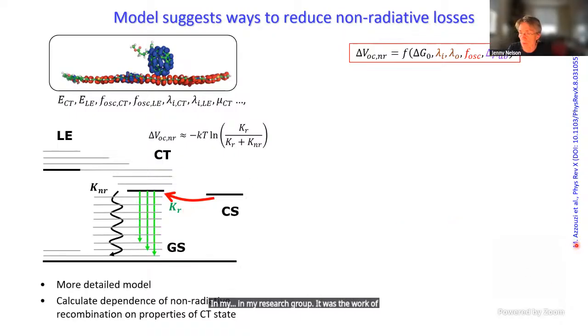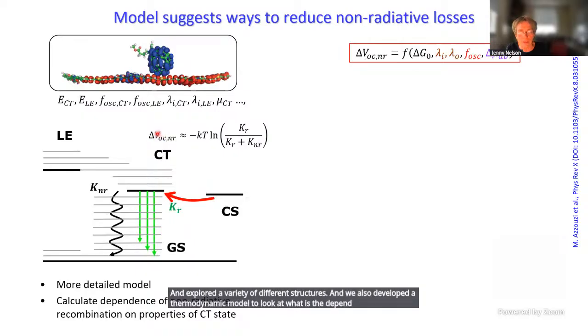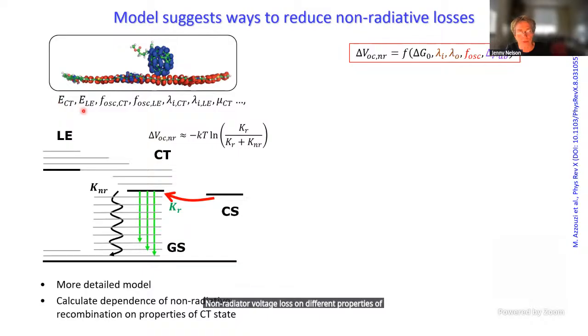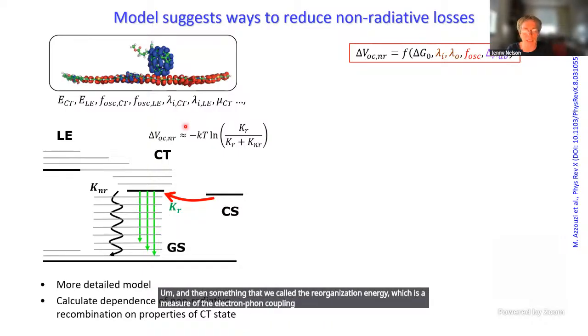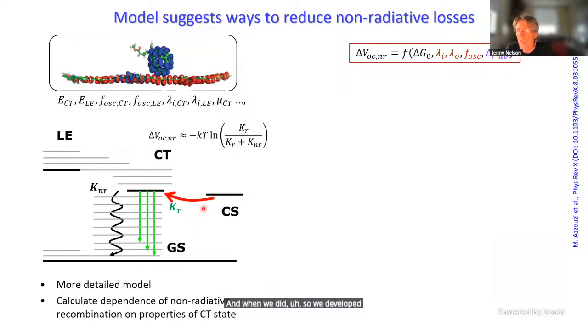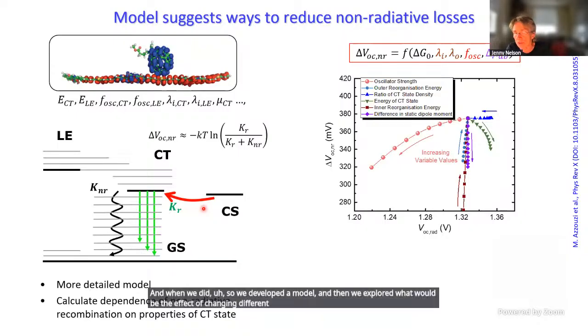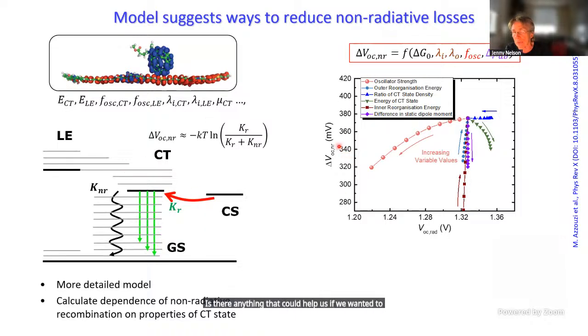It was the work of a former student called Mohammed Azuzi. We did some calculations with quantum chemistry and explored a variety of different structures. We also developed a thermodynamic model to look at the dependence of this non-radiative voltage loss on different properties of the material. It could be the energy of the state first generated by the light, so the band gap or the first transition energy of the polymer, then the energy of the charge transfer state, the oscillator strength or brightness of these states, and something we called the reorganization energy, which is a measure of the electron-phonon coupling, how easily the energy can be dissipated. We developed a model, and then explored the effect of changing different parameters. Is there anything that could help us reduce the non-radiative energy losses?